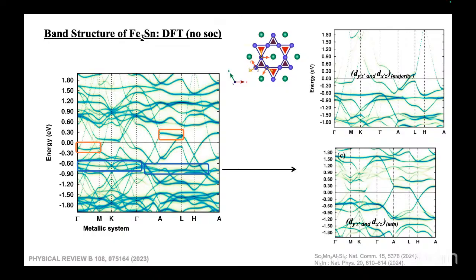Also along some paths near the Fermi level, we see non-dispersive bands along A-L and gamma-M directions. Further analyzing the orbital projected band structure, we found that the dominant contributions to these bands come from the dyz and dxz orbitals, in the majority and minority spin channels. This orbital selectivity is in line with the nickel indium Kagome system, where they also report the flat band contributions coming from these d orbitals.